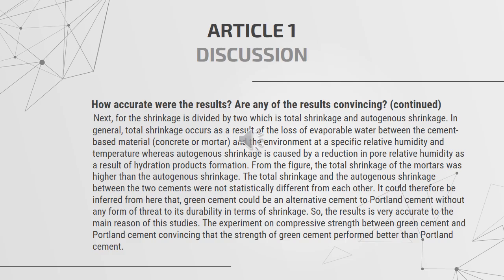From the figure, the total shrinkage of the mortar was higher than the autogenous shrinkage. The total shrinkage and the autogenous shrinkage between the two cements were not statistically different from each other. It could therefore be inferred from here that green cement could be an alternative to Portland cement without any threat to its durability in terms of shrinkage.